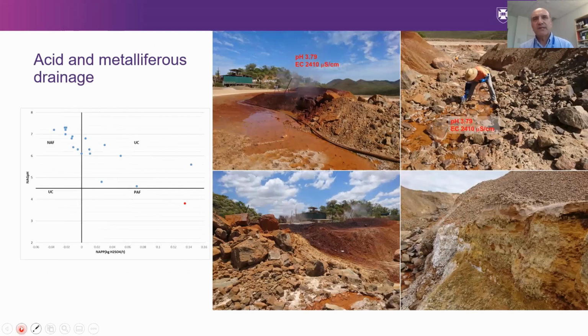Now, the issue of acid mine drainage at that site. On the left-hand side, you can see all the data for net acid generation potential and net acid production potential, two different tests that show that most of the tailings are non-acid forming, or NAF. Some of them are uncertain, and we probably need to do some column leaching. But we know from the mineralogy and the geochemistry that there is very little sulfide pyrite in there. Because the gangue minerals are granite, there is not a lot of neutralizing capacity, but we don't think that this acidity relates to the tailings.